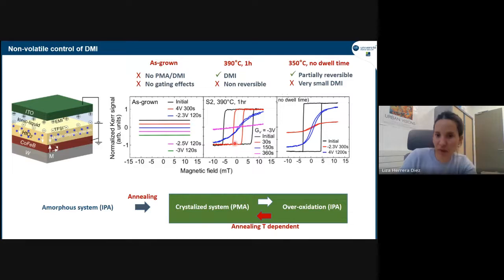But there's a main difference with respect to the previous study. Here we get DMI, which is the DMI plot that I showed you before, but it's not reversible. So you cannot go back from this pink state to the black state. And this makes sense if you think about what we're doing. We're crystallizing the system. So it's highly likely that ionic diffusion in the as-grown, amorphous state is easier than in a crystallized state, where you probably have to migrate ions only through the grain boundaries and not everywhere like you would do in an as-grown state.